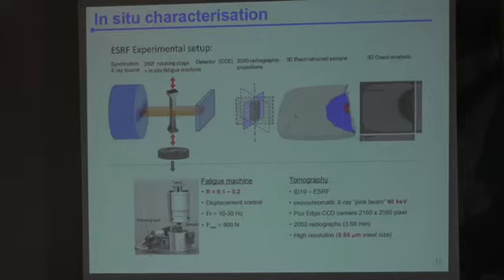And the voxel size is also an important number. It's more or less the spatial resolution. It's 0.7 micron here. Actually, as a rule of thumb, the spatial resolution is twice that number. So we have a spatial resolution which is of the order of what you can get from optical micrography.